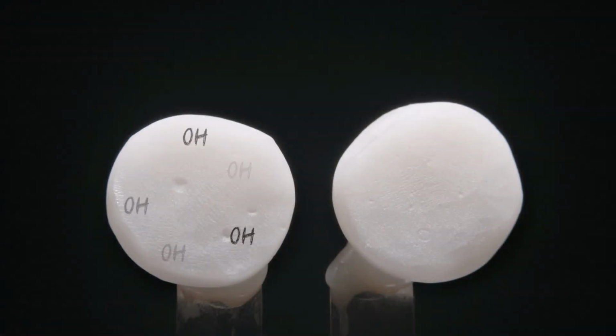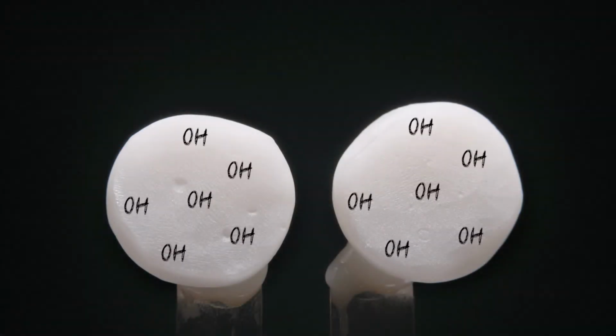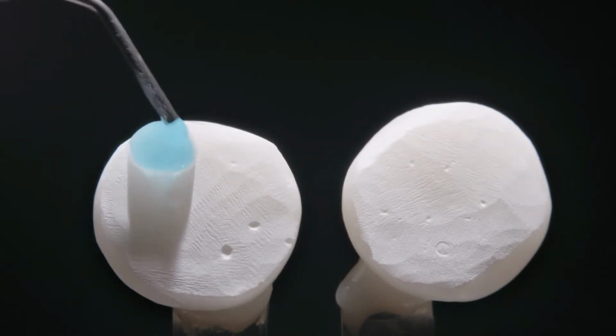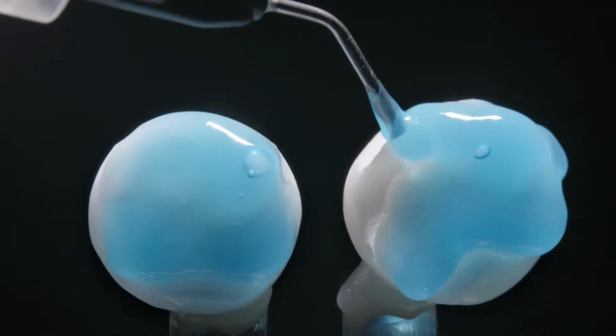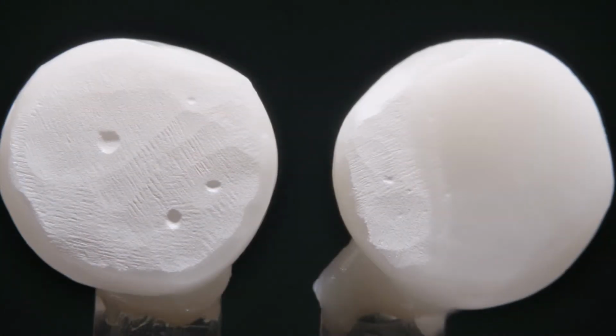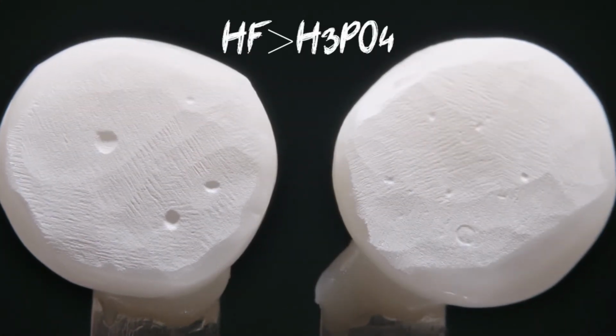Also, the treatment with hydrofluoric acid promotes the formation of hydroxyl groups on the surface of the ceramic, which are subsequently needed for silanization. The surface treatment of the ceramic with orthophosphoric acid is possible, but it's not advisable to remove the salts, since the salts of a strong acid are insoluble by a weaker acid. Although to clean the surface in the event of saliva or blood entering, it's quite effective.